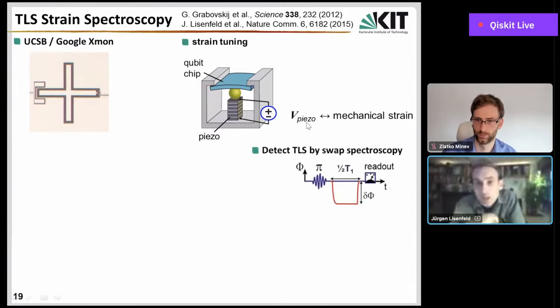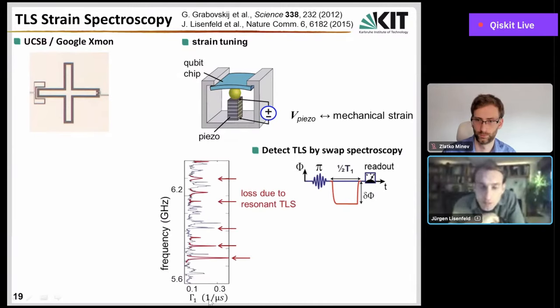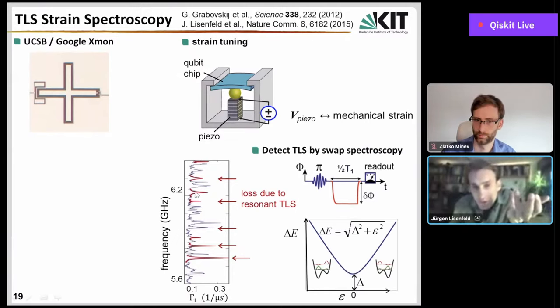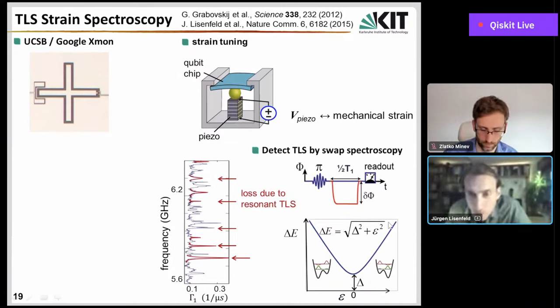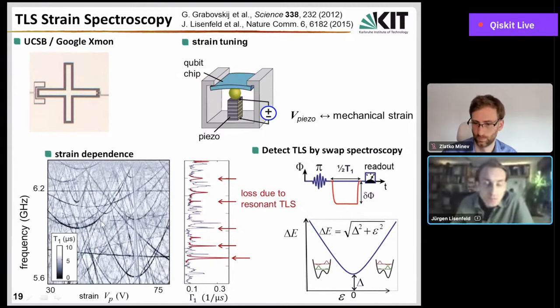Then we just basically had to again measure the energy relaxation rate of the qubit as a function of qubit frequency, again using this rather fast swap spectroscopy protocol. Our expectation was, of course, that if we change the strain, we should see that the position of these peaks follows these hyperbolic dependencies as we would have expected from the double well potential model. So we change the mechanical strain and all these peaks should move along these hyperbolas.